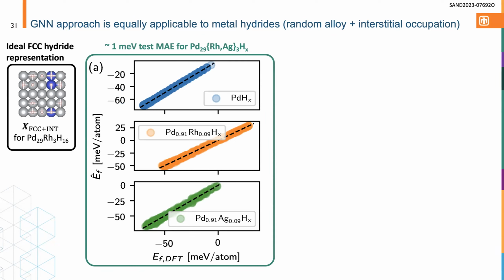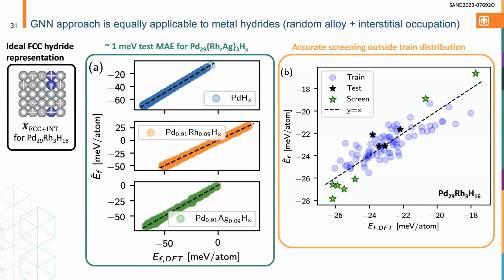We looked at palladium alloys. These are the test set predictions for the different palladium alloys across the possible hydrogen absorption range. You can see, again, the GNN is quite accurate at predicting the relaxed formation energies from this idealized representation. And again, this comments on the extrapolability, which unfortunately didn't show well in the previous slide. These green stars are random configurations for a particular hydrogen density that were identified as being lower or higher in energy than anything it was trained on. If you put those back into DFT, you get qualitatively the right results: indeed these energies are lower or higher than anything the model's been trained on.